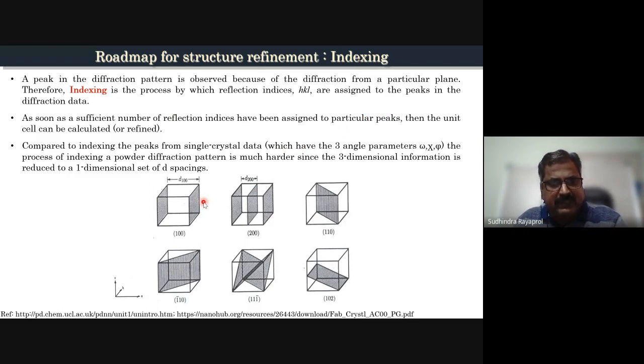For a cubic structure, you can actually determine the cell parameter from one peak, from one index, and it should be identical for any of the HKL values or any of the peaks which you choose. In the case of tetragonal or hexagonal, you need at least 2 peaks. In the case of orthorhombic or any lower symmetry systems, you need 3 or more peaks to determine the cell parameters. Compared to indexing in single crystal, where you have three angle parameters like phi, chi, and omega, indexing powder diffraction is much harder, since three-dimensional information is reduced to a one-dimensional set of d-spacings.